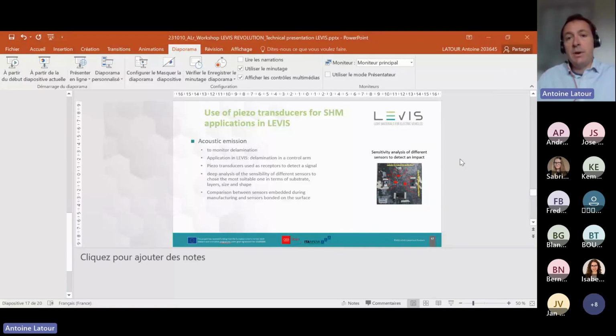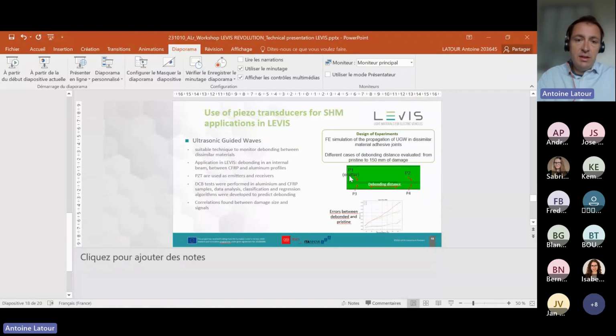We are making some comparison between sensors embedded during the manufacturing process, so under the resin, but also a sensor just bonded on the surface. You can see here a picture of some sensors embedded in the composite foil, and we are conducting the sensitivity analysis with that. For the other technique, the ultrasonic guided wave, this technique is more suitable to monitor